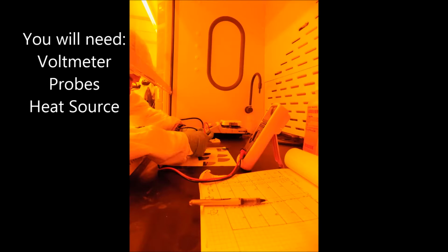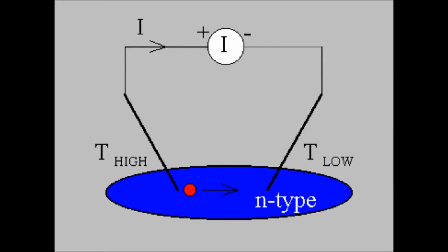The negative probe will touch the region of interest, and the positive probe will be heated up. When the hot probe touches the region of interest, it will induce a current via thermal excitation. The region type, N-type or P-type, will be determined by the polarity of the current induced.